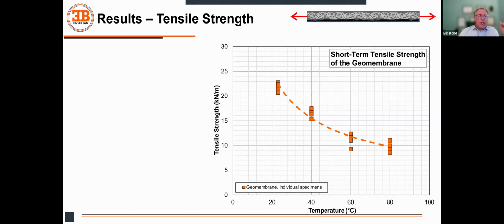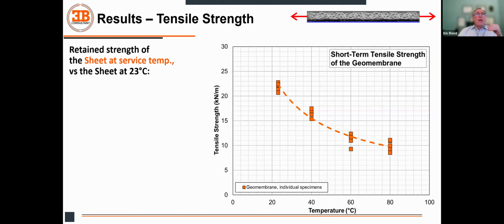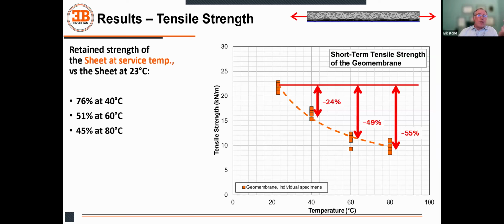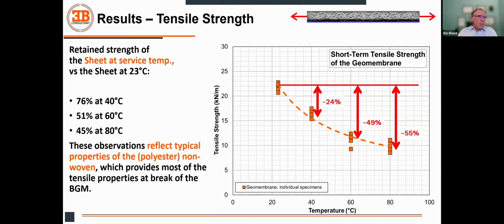So that's really only the sheet which is exposed to a tensile stress. What we see is that there is about 25% loss in terms of sheet strength at 40 degrees Celsius versus the value that we've measured at 23 Celsius. We have lost half of the strength of the sheet at 60 Celsius and 55% at 80 Celsius. And this is all very normal because with any polymeric material we would observe something quite similar, with polyethylene, polypropylene, or any other geomembrane. The temperature will affect the sheet strength of the product.